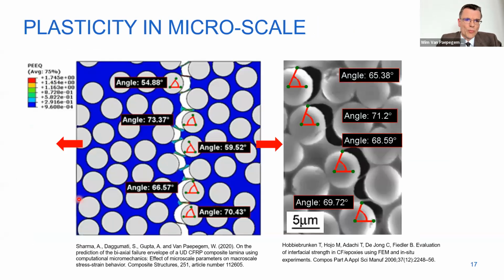When we zoom in more, when these bonds start to coalesce together, you also see a large plastic deformation in the polymer. And these fibrils of polymer stretch a lot. We try to validate not only on transverse strength, but also on opening angles of debonding. For example, Hobbiebrunken's famous pictures show these polymer fibrils that stretch.